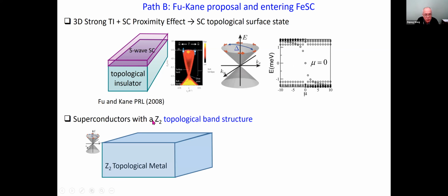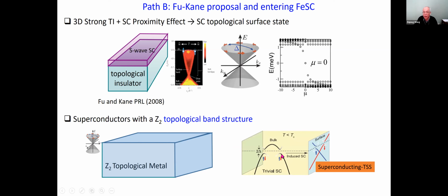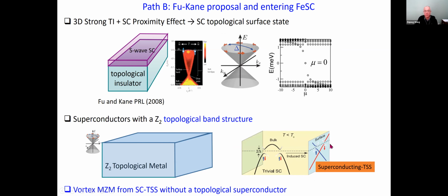But this one superconductor should have a Z2 topological band structure. So therefore, your starting point should be a Z2 topological metal. That is to say, maybe a doped topological insulator. So both the bulk bands and the surface states are doped. Now, if you manage to make this guy superconducting, you would gap the bulk states, and you would necessarily induce a paired state on the topological surface state. So this is a way of achieving a superconducting topological surface state. And once you have that, you have vortex Majorana zero mode.